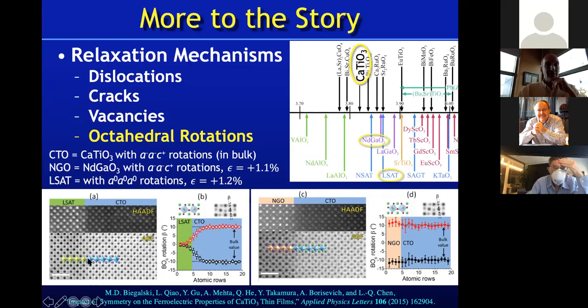You can see that the story in going from LSAT to calcium titanate looks like one in which the LSAT has no rotations. I mentioned that LSAT is very, very close to being cubic. It's slightly tetragonal, but even in tetragonal, the Glazer notation to describe the rotations along the axes, these a, b in-plane axes and the c out-of-plane axis, would be that there's no rotations. So we go from having a substrate with no rotations to calcium titanate, which has rotations.